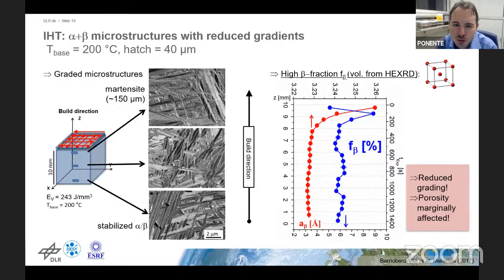And XRD here shows a little bit this trend. On the left-hand side, the axis shows the height of the cubic specimen, 10 millimeters. And the blue curve shows the volume fraction, again, of the beta phase in this case. And in the stabilized region, which extends to roughly 8 or 9 millimeters here, 8.5 millimeters, you have roughly 6 to 7% of beta phase in this cubic specimen. Whereas at the top of the specimen, you switch to a martensitic microstructure with very little beta phase here near 10 millimeter height. So that's something to keep in mind.